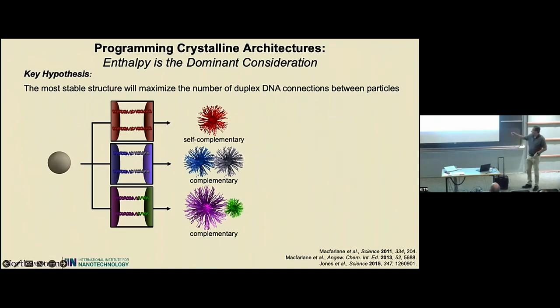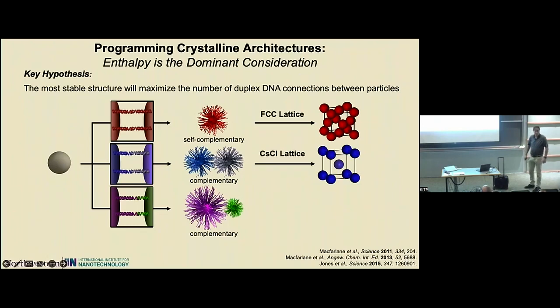So if you want to make an FCC structure, you make self-complementary particles. That's easy with DNA, GC. If you want a BCC or cesium chloride type lattice, which you've heard about already, you have two particles of the same size that are complementary. And if you want to begin to make more exotic structures, you begin to play with the size ratios, which you can modulate based upon the choice of particles, the cores themselves, and the length of the oligonucleotides. And that's the other thing. You can change effectively the size of the programmable atom using those two parameters.